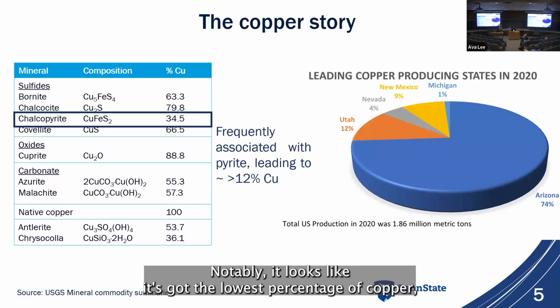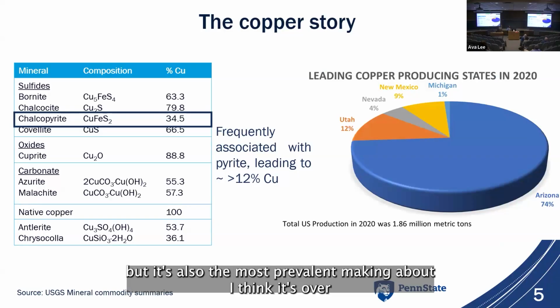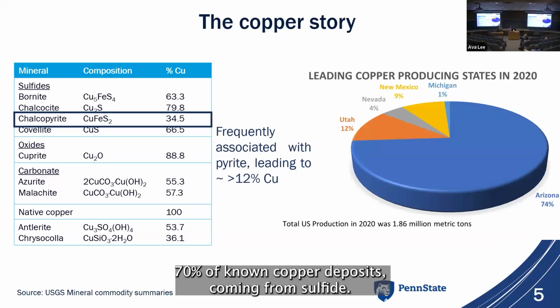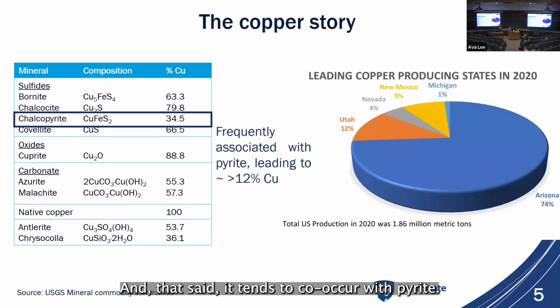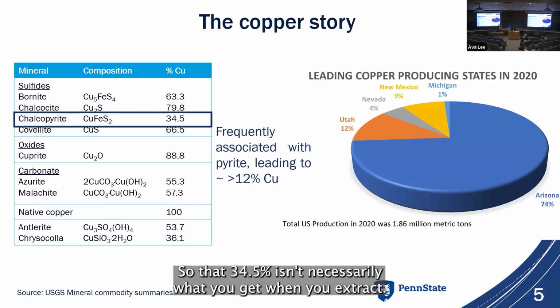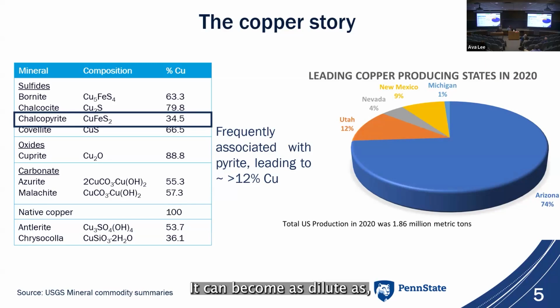Notably, it looks like it's got the lowest percentage of copper, but it's also the most prevalent, making about, I think it's over 70% of known copper deposits are coming from sulfide. And that said, it tends to co-occur with pyrite, so that 34.5% isn't necessarily what you get when you extract. It can become as dilute as less than or just above 12%.